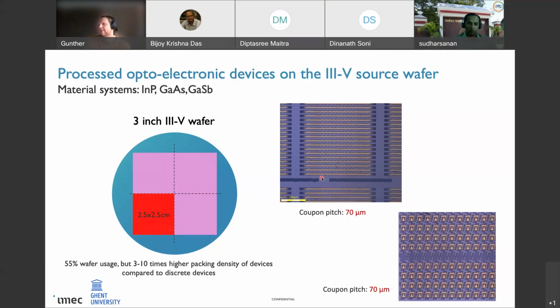However, the devices themselves are extremely small. Typically, you can put devices like a waveguide-based amplifier on a pitch of about 70 micron on the III-V source wafer, in one dimension, of course. In the case of a square device, like a photodiode, you can put them on a 70 micron pitch both in the X and the Y direction. If you compare that to a classical flip chip type device, these pitches there are typically a factor of 3 or 4 higher. So we're talking about dies of 200 micron to 300 micron in width.